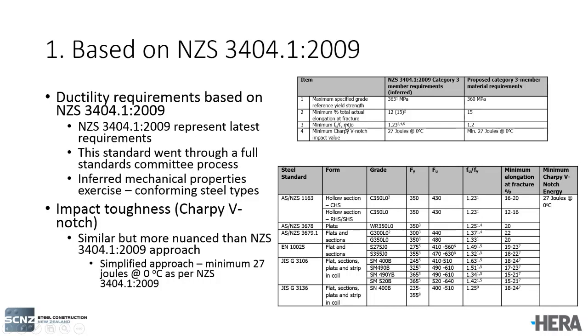If you look at the minimum FU over FY ratio, it's 1.23, and it varies between 1.23 and about 1.6-ish, and we've settled on 1.2. There's a minimum of 27 joules for the conforming steel types, and we have in our proposal that the steels must have a minimum of 27 joules. So our method's slightly more nuanced. What we're saying is that 27 joules at 0 degrees will often apply, but there may be some applications, such as steels that are very thick or steels that are operating at a very low design service temperature, where that 27 joules at 0 may be inadequate, and steels with a higher minimum Charpy impact value might be required.